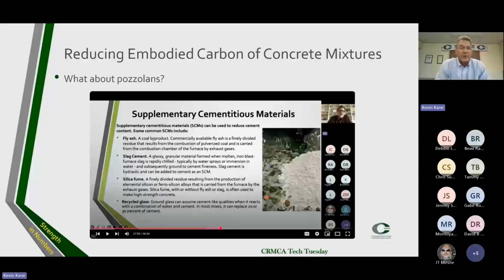Supplementary cementitious materials. What about pozzolans? Oh my gosh. When I first got in the business 35 years ago, we basically had one pozzolan, and that was Class C fly ash. Cut my teeth on Class C fly ash. Now it's kind of hard to find Class C fly ash. Class F fly ashes came around in the late 90s. And when I first switched from Class C to Class F, I was wowed by the benefits of Class F. Class F fly ash, while it doesn't have the strength activity of Class C, has a lot of other attributes: sulfate resistance, ASR mitigation. Class F fly ash is much easier to use.